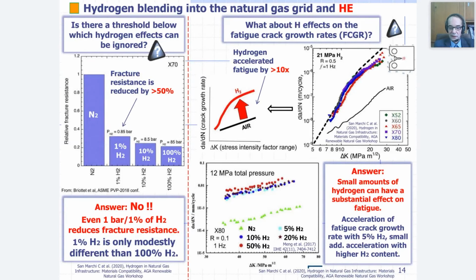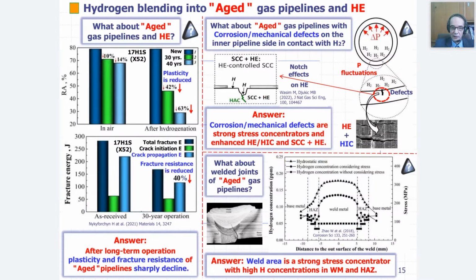As you can see in the upper right section, the same applies for almost all grades of steel. So we have a very similar enhancement of fatigue crack growth rate for various steels from X52 up to X80. So generally, hydrogen accelerated fatigue by almost 10 times or higher due to the hydrogen embrittlement effect. The next important question I already mentioned: what about aged, old gas pipelines and hydrogen embrittlement?